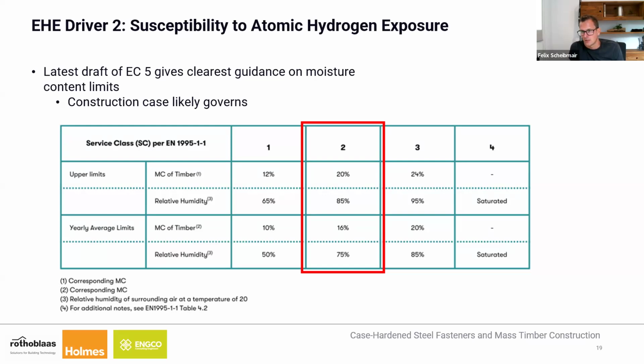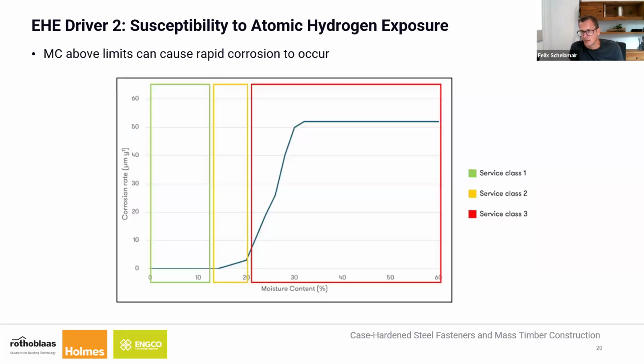So what we're trying to say there is that really we want to be more around that 16. Those upper limits are just that. 20% is the very top of that range, and once you step over that into your class 3, you start to see an acceleration in the corrosion that you get.